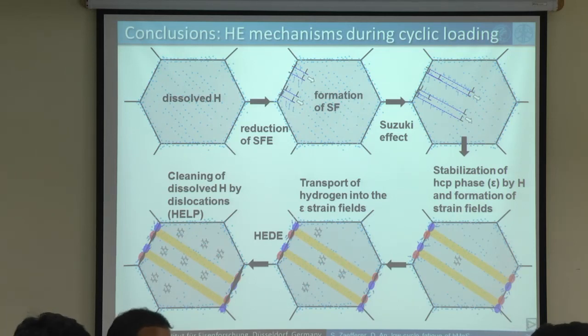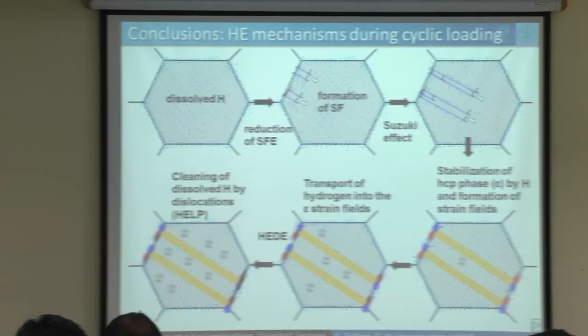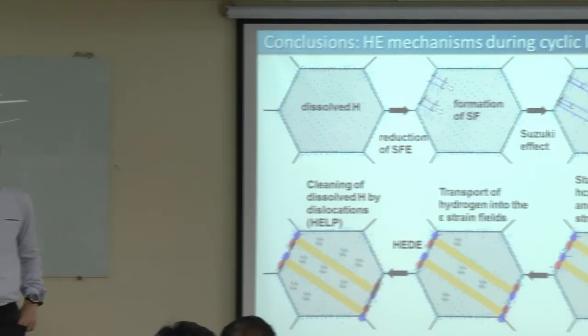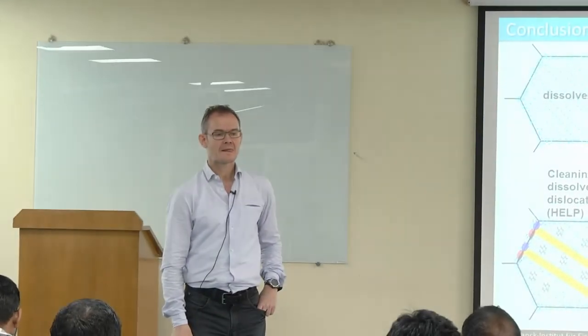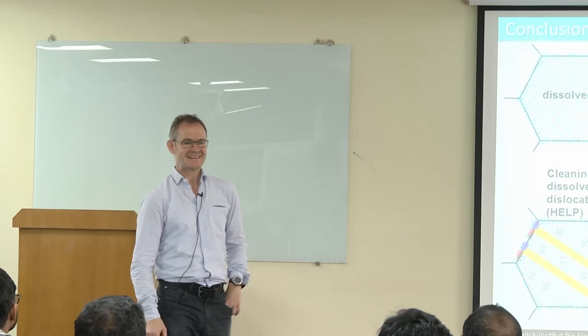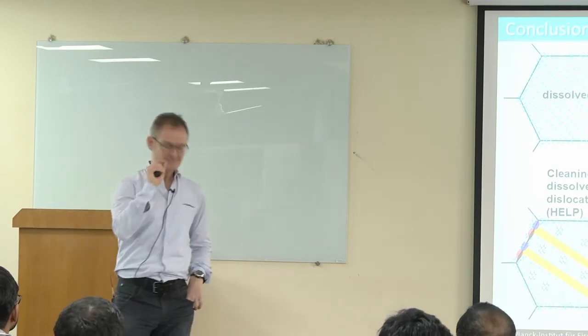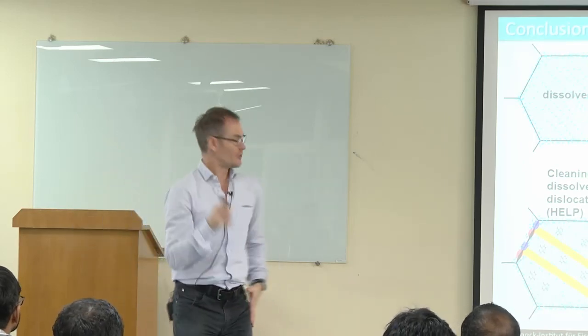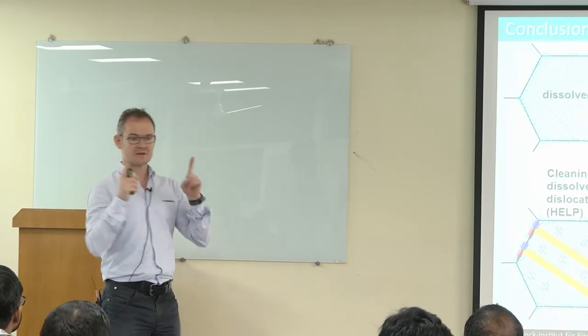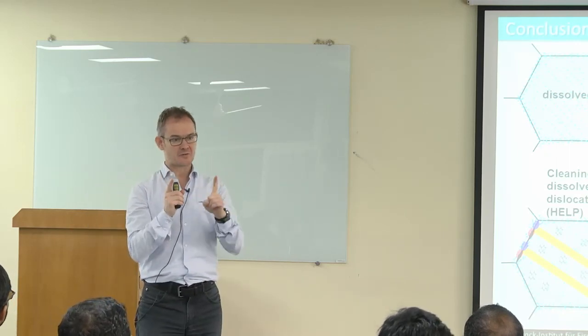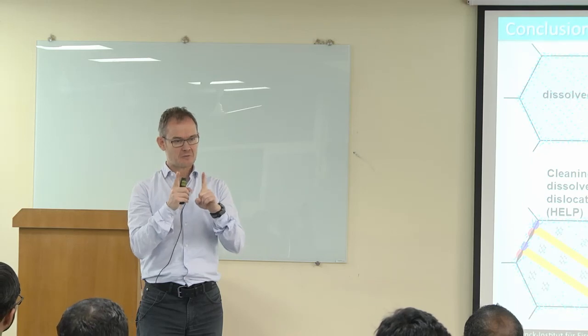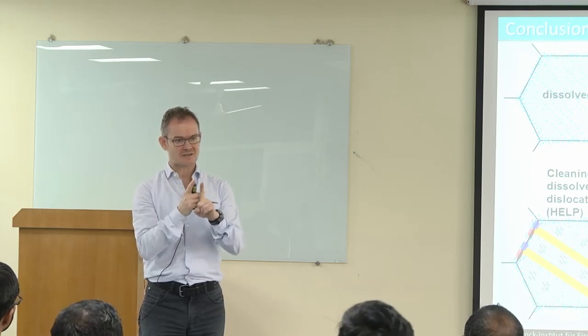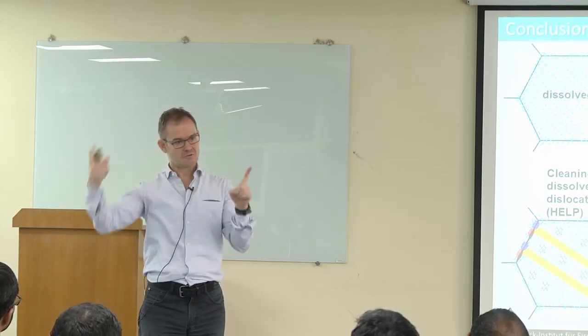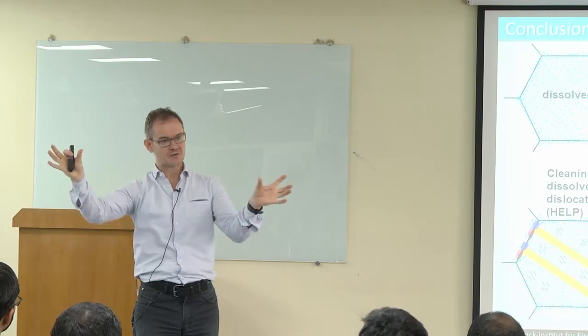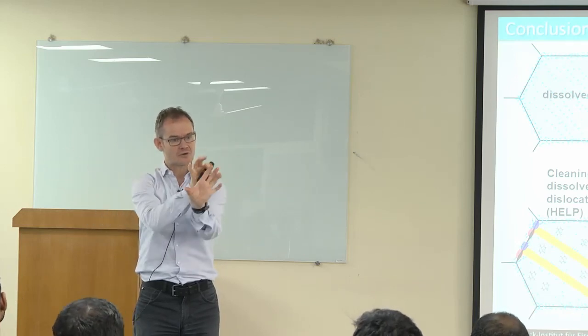Very good. How can we use the cross-correlation technique that you mentioned for calculating strain across phase boundaries or grain boundaries? This is a very good question. For the cross correlation, you always need a reference pattern, and this reference pattern must be almost identical to the measured pattern. That means if you have a grain boundary in between, the pattern looks completely different, and you can no longer do any cross correlation.